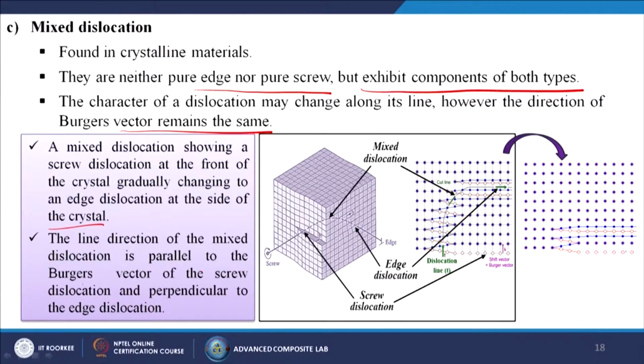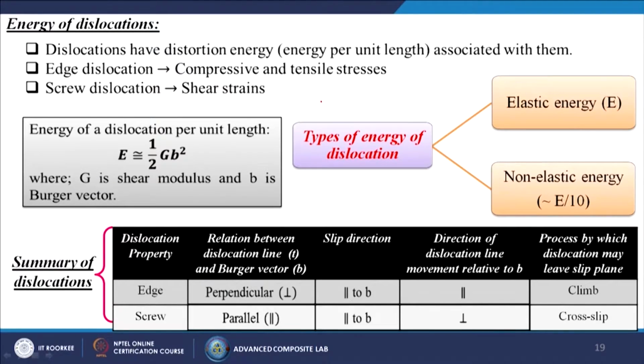So, the line direction of the mixed dislocation is parallel to the Burgers vector for the screw dislocation and perpendicular to it for the edge dislocation. Next, energy of dislocations. Dislocations have distortion energy, energy per unit length, associated with them. Generally edge dislocations involve compressive and tensile stresses, and screw dislocations are mainly for shear strains. So, the energy of a dislocation per unit length E is more or less equal to half G b square. What is G? G is the shear modulus and b is the Burgers vector.